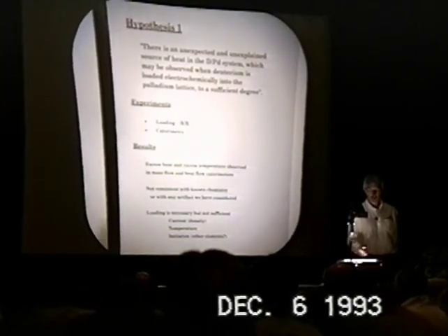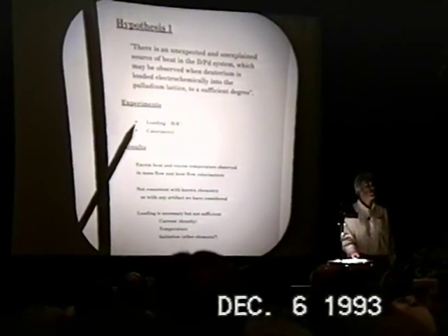Suggests experiments both in the field of loading, to understand how to insert and maintain high loading levels of deuterium inside the palladium lattice, and calorimetric measurements in order to investigate this potential heat source. The results that we have obtained and have discussed previously, excess heat and excess temperatures, are indeed observed in mass flow and heat flow calorimeters. That these heats, energies, and powers are not consistent with known chemistry or with any artifact that we have considered.